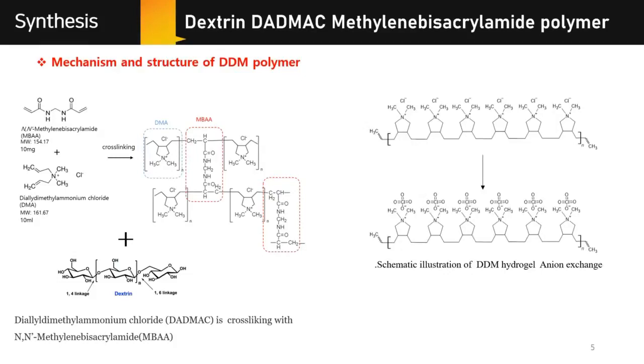DDM gel electrolyte has a double network structure. The hard and soft components of the double network make the DDM gel flexible and tough. This chemical structure has the advantage of overcoming the drawbacks. The first network polymer was synthesized by a free radical polymerization technique using KPS as an initiator. MBAA works as a cross-linker in this reaction, and DADMAC is the monomer.